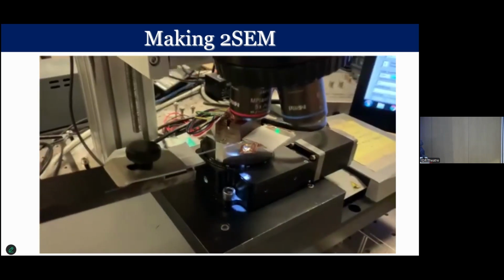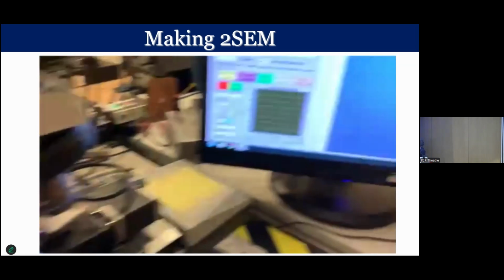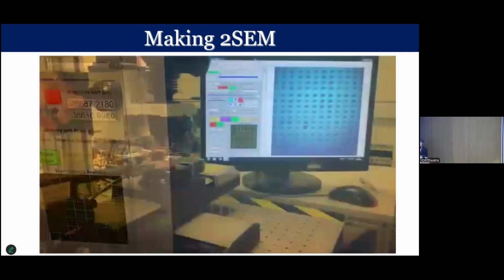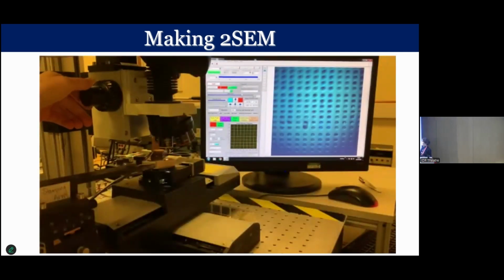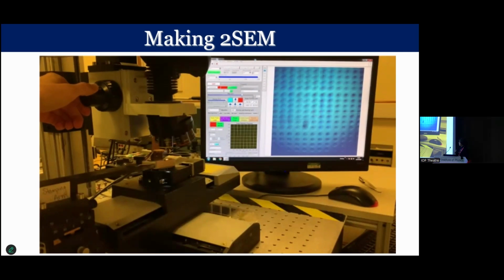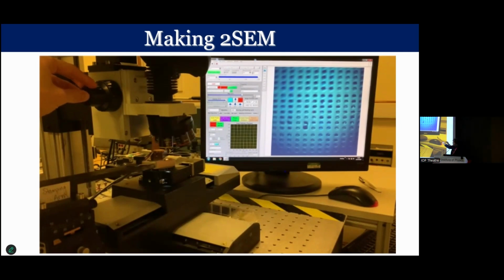So for this technique, we use a glass needle that has been formed with a very fine tip, which is about 10 microns, similar to our graphene strips. The first step is to bring the needle close to the graphene strips, and we can do this by changing the focus of the microscope between the needle and the graphene, and then adjusting the micro manipulators on the stamping arm to bring the needle down.